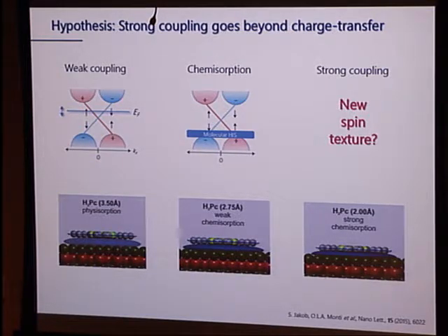Let us imagine that we have some molecule that interacts very weakly with the surface. This falls into the realm of what people would call physisorption. And in that case, the only thing that happens is you change energy levels around a little bit, but nothing serious happens. So that's the situation that I'm showing here. You have your topological insulator material, and then you mildly doped it, either by pulling electrons out a little bit, by exchange correlation, or maybe by pushing electrons into the surface a little bit, and that will shift the Fermi energy a tad.